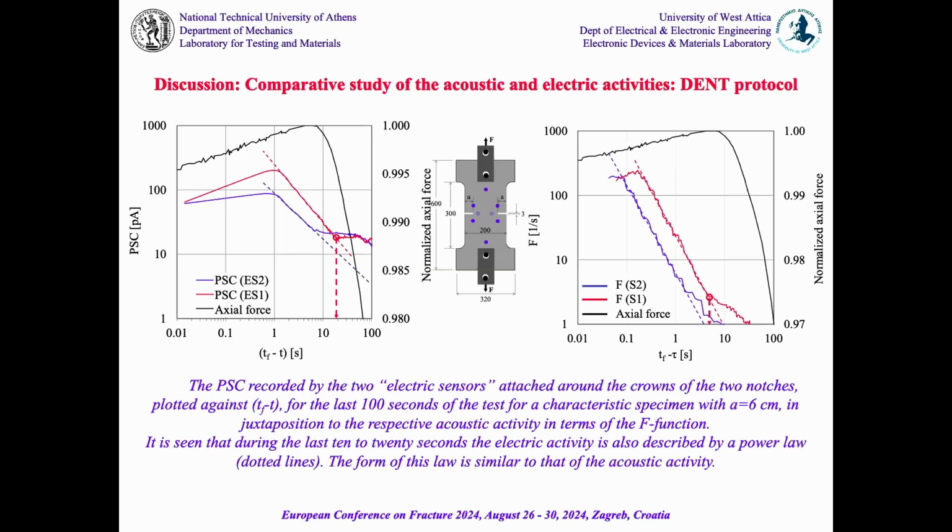We will not need to comment on these conclusions, which means that we have an additional tool in our hands, besides the well-established technique of acoustic emissions: the tool of pressure-stimulated currents, which has an advantage. Not only does it predict the critical point somewhat earlier, but it is very cheap.